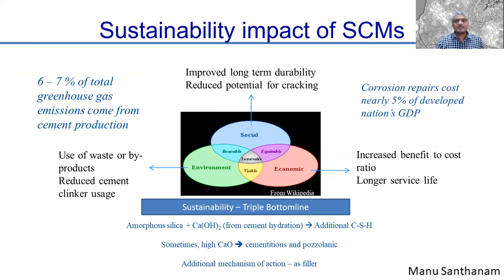Right. So what are these supplementary materials doing? Primarily, these materials consist of amorphous silica, right? And this amorphous silica basically combines with the calcium hydroxide from cement hydration to form additional calcium silicate hydrate. That's the primary impact of supplementary materials. But I'll show you as the lecture progresses that you can have some secondary impacts also. Formation of other products sometimes also happens, and this leads to a complete filling up of the pore structure, and that ultimately leads to better durability.